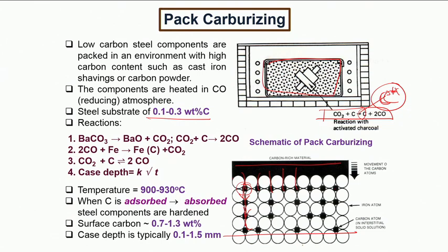On the other hand, depending upon the time that you allow, this time essentially determines to what depth you can expect carbon to diffuse in. We also have seen that the carbon diffusion profile decays with depth. So, as we go lower and lower, the carbon content decreases. Obviously, the surface which is exposed to the carbon rich environment will have the maximum amount of carbon, and way below inside you will have the least amount of carbon.